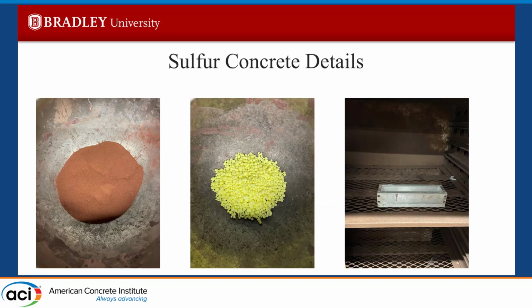And then after the time's up, you'll notice it's all one consistent color, kind of like you're baking a cake. Once that's ready to go, you'll take the mold out, put it onto a shaker table, take the bowl with the freshly melted sulfur and Martian soil combined, mix it before you pour it, and pour it into the mold on the shaker table while it's running low to medium. You don't want it too high. The shaker table is essentially to make sure that when the liquid is poured into the mold, it settles and doesn't have little air gaps in there.